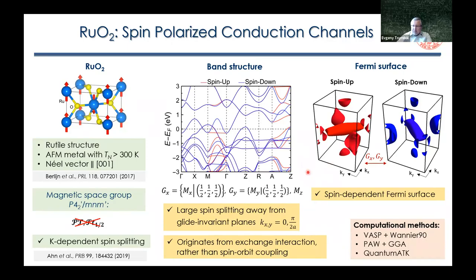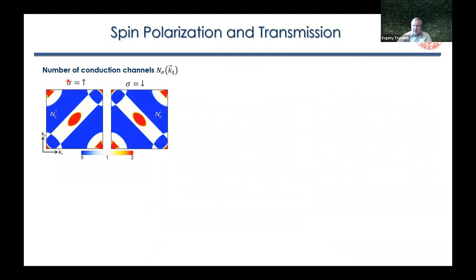What is important from the point of view of transport properties is the number of conduction channels. So it's the number of states which are contributing to the conduction. Here we're considering the 001 direction for the conduction. Therefore, the number of conduction channels is plotted in the two-dimensional 001 Brillouin zone for spin up and spin down channels. Obviously the number of conduction channels is an integer, 0, 1, or 2, shown in color here.